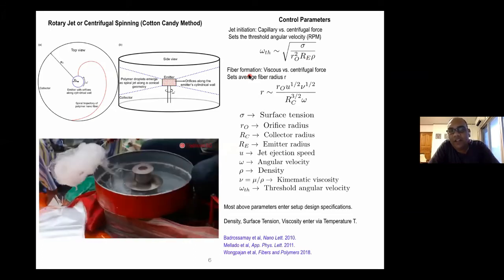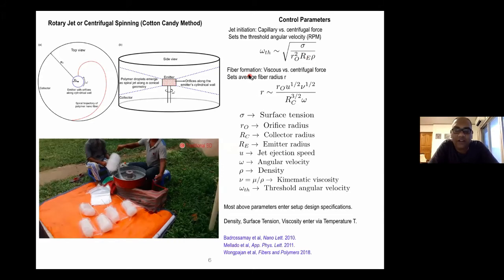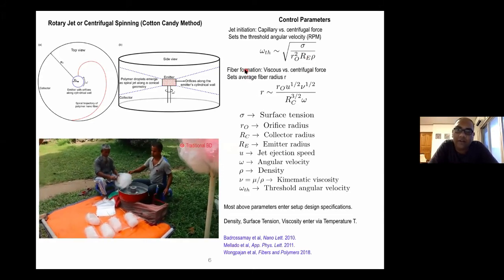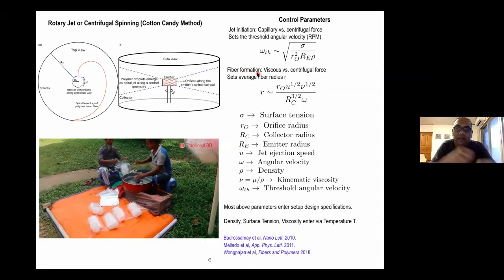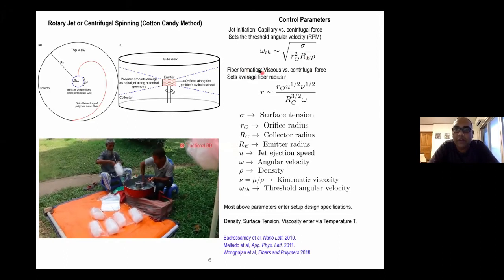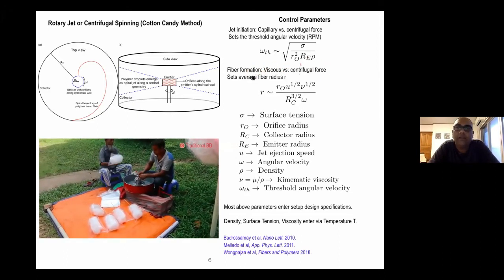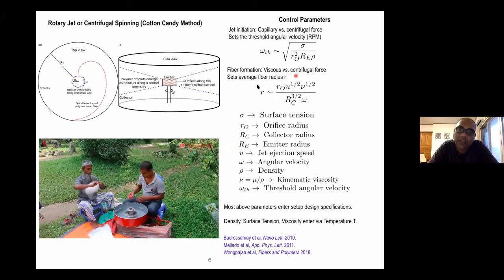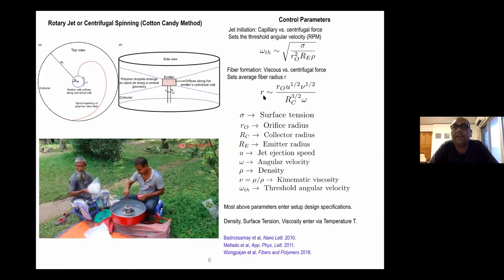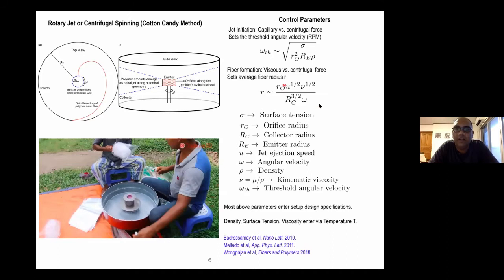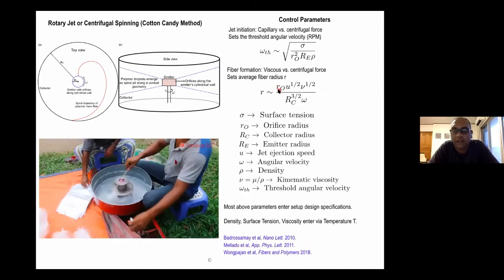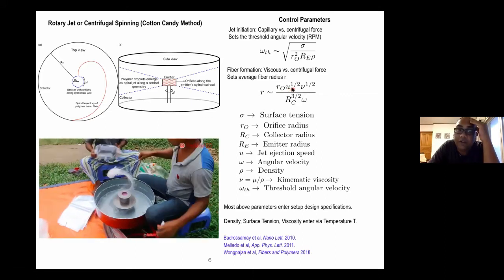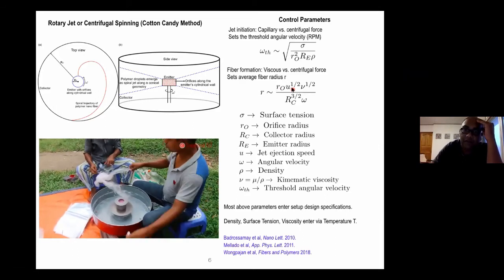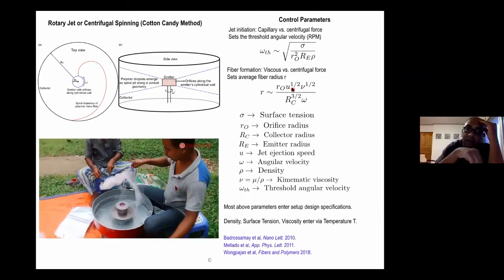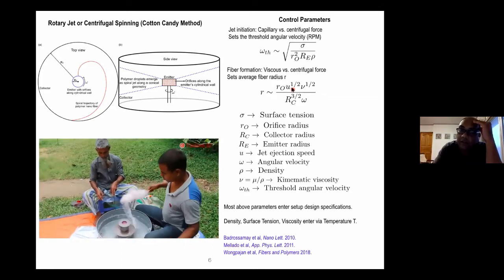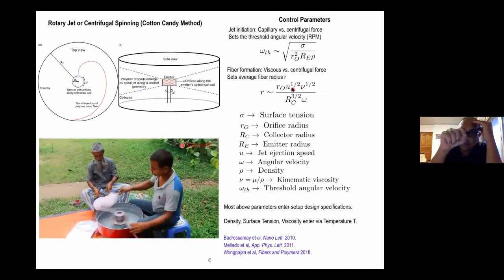In the second stage, once you have initiated the jet, it is now going to get forced out of the orifice, and it will execute the spiral trajectory. That is a case of extensional rheology, as I said. There you have viscous force competing with the centrifugal force. When you balance these two, they showed that the mean radius or the average radius of the fibers that are generated scales as this expression. This is the orifice radius times the square root of the velocity at the time the jet is ejected from the orifice. As it traverses the spiral trajectory, it is of course going to slow down, but that is not the velocity they take. They take the velocity at the time that the jet is initiated.